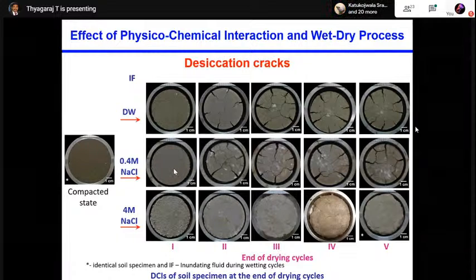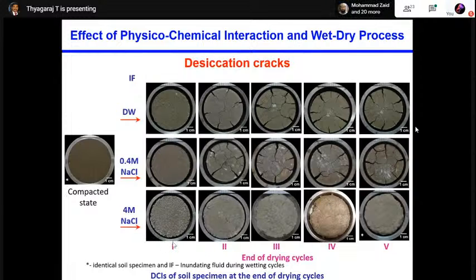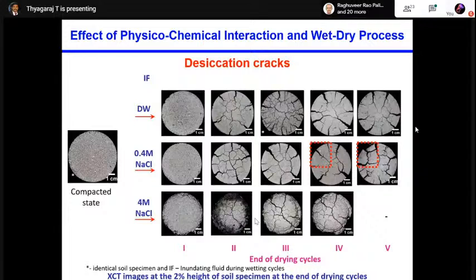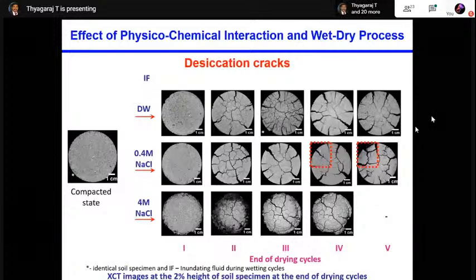With the 0.4 molar, the behavior is more or less the same. But with the 4 molar NaCl solution, you can clearly see that the volumetric shrinkage of the specimen is very small. The cracks are not much visible on the surface. But when we took an XCT, we saw that there are a lot of cracks. This is the XCT, just 2% below the surface depth. These are the cracks, and if you go deeper, a lot of cracks are there.